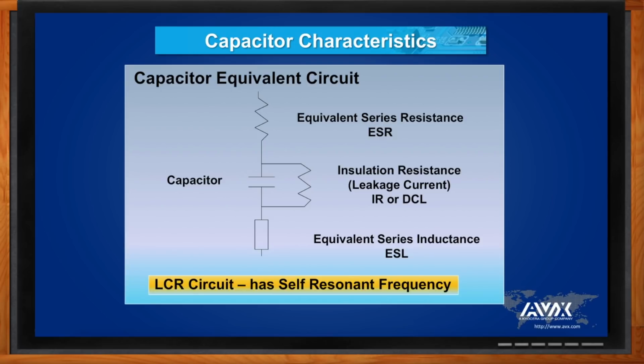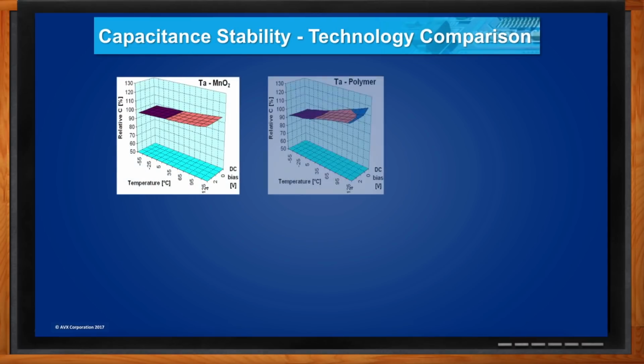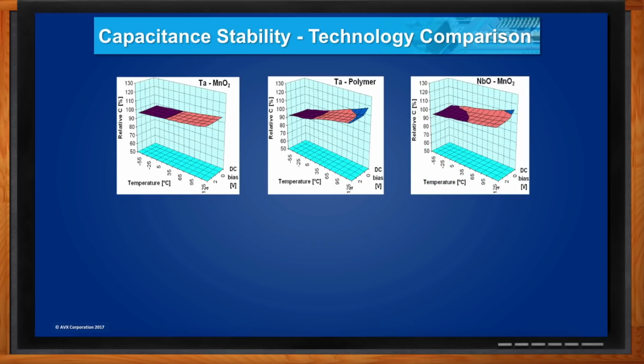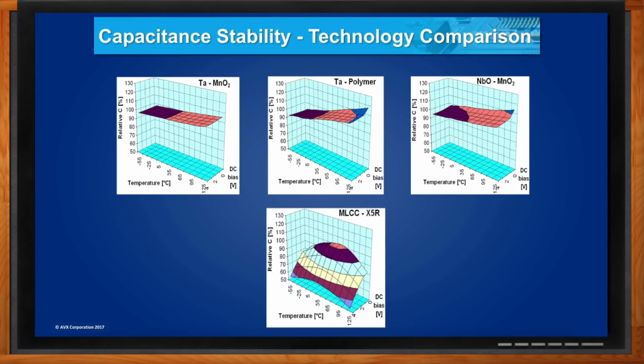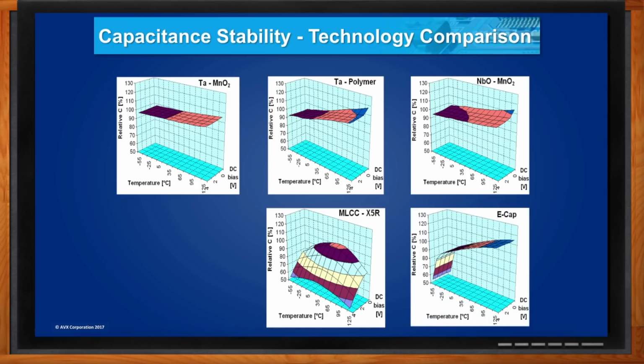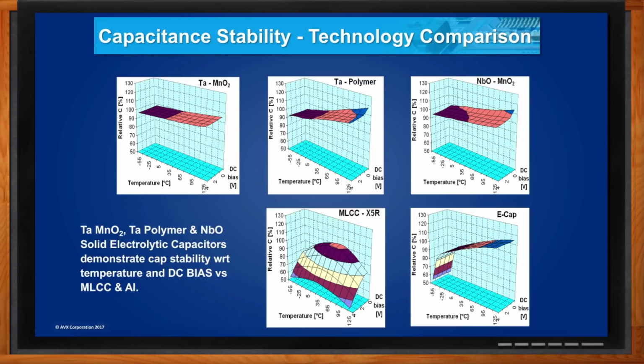If we look at the capacitance stability, the electrolytic family of tantalum and niobium that include the polymers, we've got a very, very flat temperature characteristic over minus 55 to plus 125, 15%. If we compare that with an equivalent capacitance class 2 ceramic, such as the X5R, you'll see it has a sweet spot there, but the capacitance drops rapidly at high temperature, low temperature, and as you apply voltage. So there's a voltage coefficient effect there. Now, aluminum hasn't got the disadvantage of a voltage coefficient, but it does lose a lot of capacitance at the low temperature end. So there's definitely temperature characteristics to be considered here.